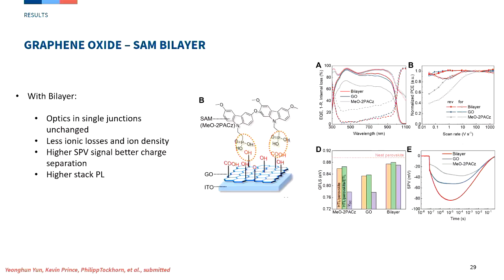So we changed the binding affinity by using graphene oxide underneath. So now the same molecule, here's the phosphonic acid binding group, has more OH groups and has a stronger binding, and now is less sensitive to the additive that you use, and you can get a higher film quality without penetrating the molecules to the top surface that you don't want to have.